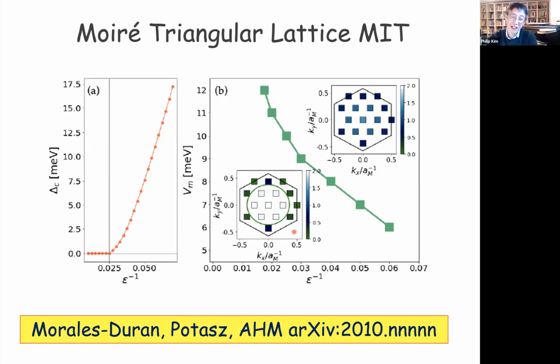I see. But the gamma point is really the gamma valley is a really distances of far, right? Because that is not necessarily kind of direct band gap regimes. So hybridization might be kind of quite weak, I guess. No, at the gamma point in the Brillouin zone, the hybridization between the layers is very strong. And that's actually the reason why bulk materials have valence band maximum at gamma, whereas when you narrow it down to a single layer, the valence band maximum is at K. And in most homobilayers, then already at bilayers, the valence band maximum is indeed at gamma. So these should be the low energy states of the valence bands in molybdenum disulfide, diselenide, and tungsten disulfide also, I think.